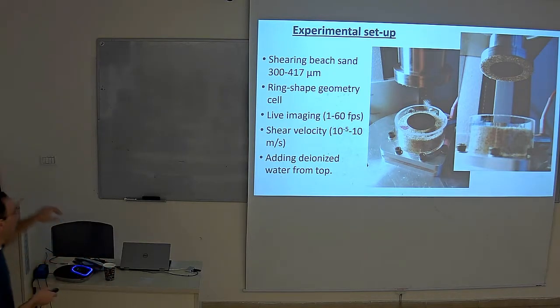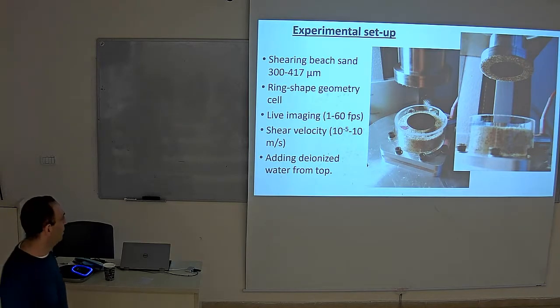We have a ring-shaped geometry that I designed, and the idea is to have less variability in the velocities. Instead of a cylinder, where we have a variability in velocities from 0 at the center to the maximum, and that's important, I think. Live imaging, we can see through the glass jacket, so we can take a look at this part, with 1 to 60 frames per second. Shear velocity is between 10 to the minus 5 to 10 meters per second, so we can get all of the range of the inertial numbers there. And in order to run it saturated, we're adding deionized water from the top.